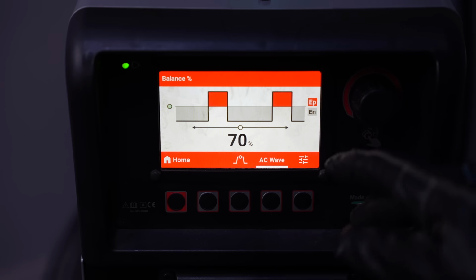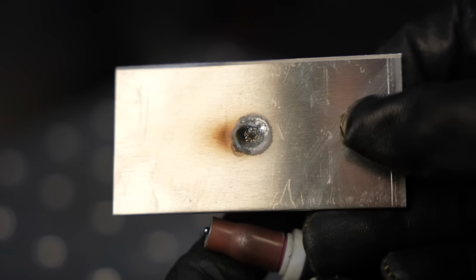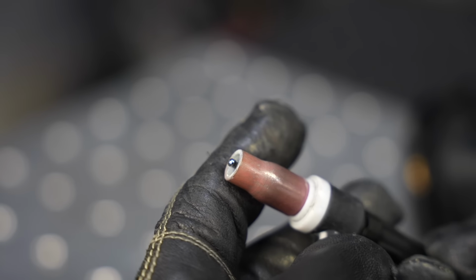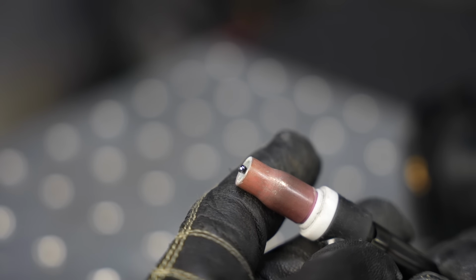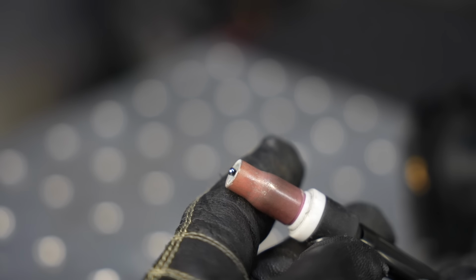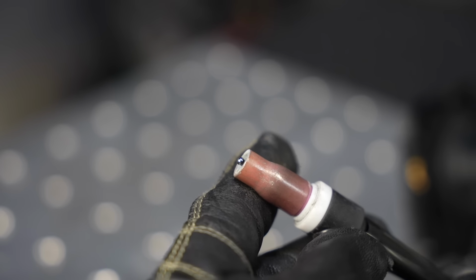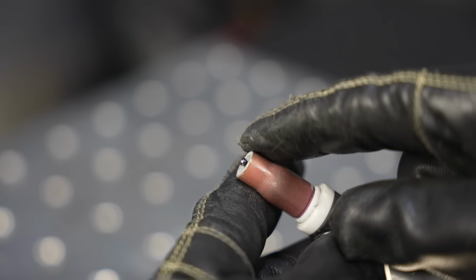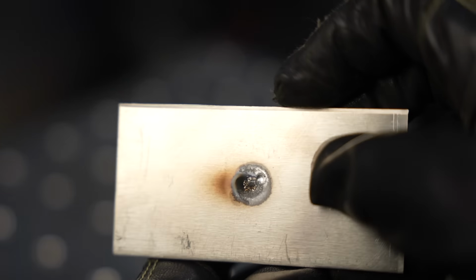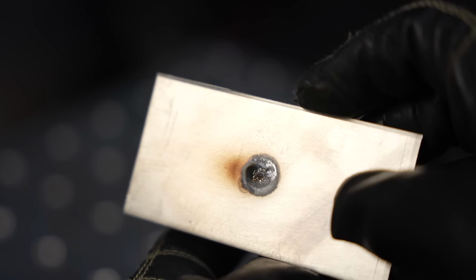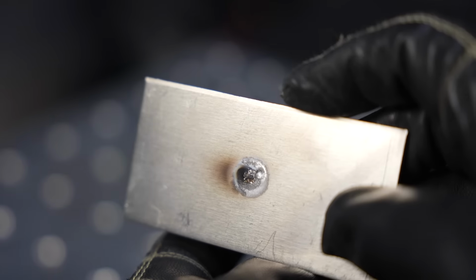You can tell if you're backwards of that if your tungsten electrode just balls up all of a sudden. With the balance backwards, it hardly melted the material and the tungsten electrode looks like a Tootsie Pop. Now the reason for this is balance ultimately controls how much heat goes into which side of your arc. So when I have it backwards, it's putting most of the heat into the tungsten and not enough into the metal. And so I just need to adjust that to be the opposite.